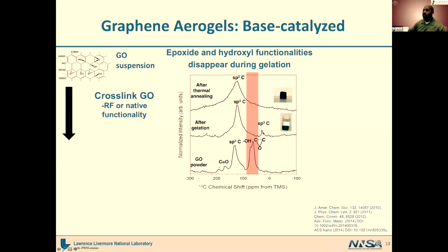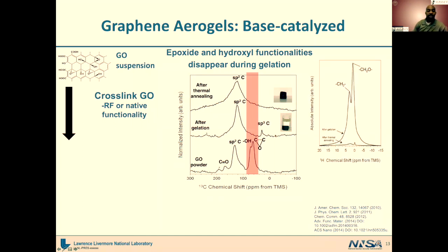And you have this sp3 carbon peak now appearing. Now this sp3 carbon, if you then go do hydrogen NMR, you would find that these are actually methylene and methylene oxide sort of bridges, which are analogous to what you see when you're actually making a resorcinol formaldehyde gel. And when you then take that gel, you dry it, and then you heat it in order to remove the organics and just have your carbon left over, you see that those peaks go away because you're now removing any sp3 carbon and are only retaining the sp2 carbon.